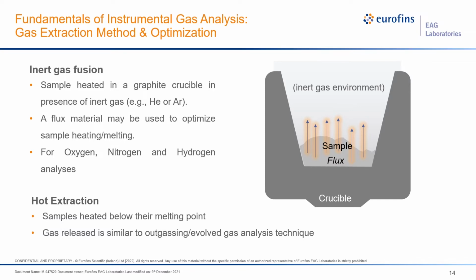On this slide, we are looking at two different methods that can be used for gas extraction. Inert gas fusion can be defined as gas extraction performed in an inert gas environment. For example, the sample is heated in a graphite crucible in the presence of helium or argon. Sometimes a known amount of flux material is used to enhance the extraction by lowering the sample's melting point and promoting chemical reaction to optimize gas release. The method is mainly used for oxygen, nitrogen, and hydrogen analysis.